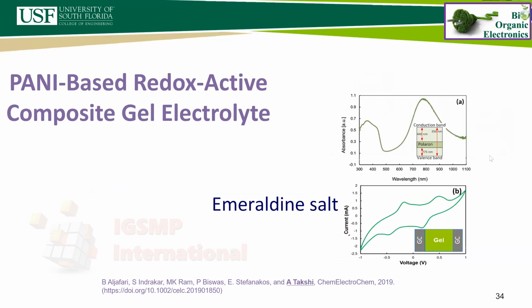So we took that gel and simply put it between 2 layers of glassy carbon electrodes. For those who have worked with glassy carbon electrodes, they know that it's very conductive, but it's a non-porous electrode. It's a very shiny surface. So typically you don't expect much electrochemical capacitance because of the non-porous structure of the electrode. But surprisingly, we saw that we are getting very good capacitance. And not only that, we are able to identify that the redox state of the polymer, polyaniline, is changing as we charge the device.